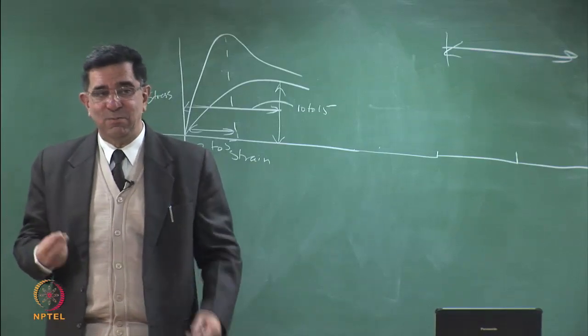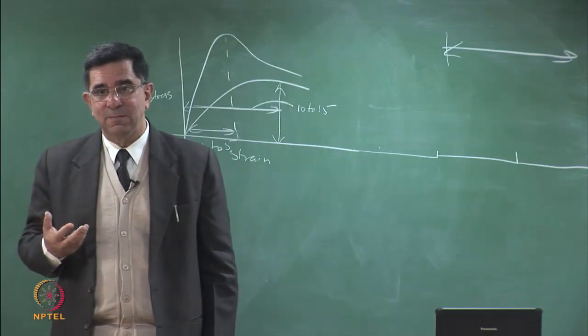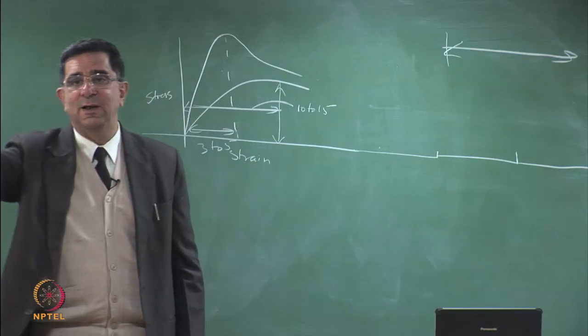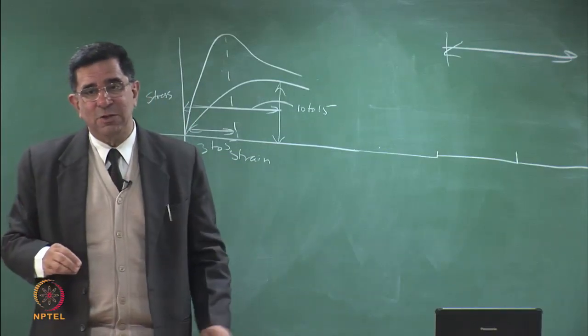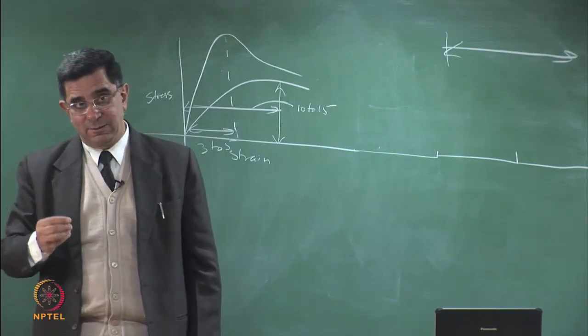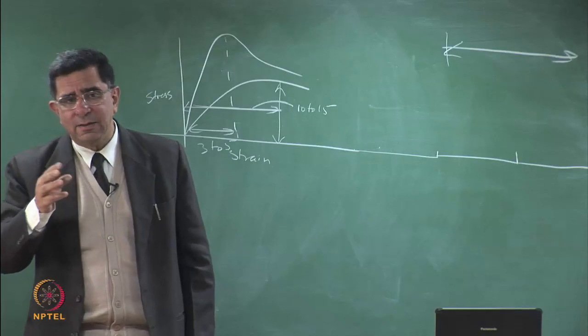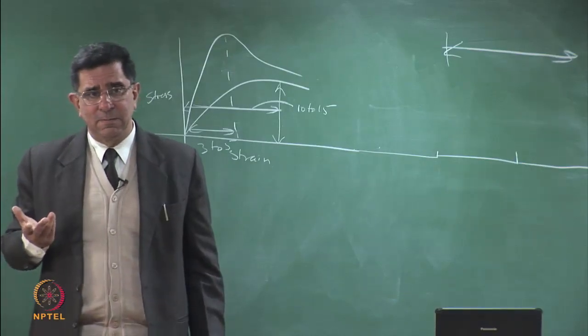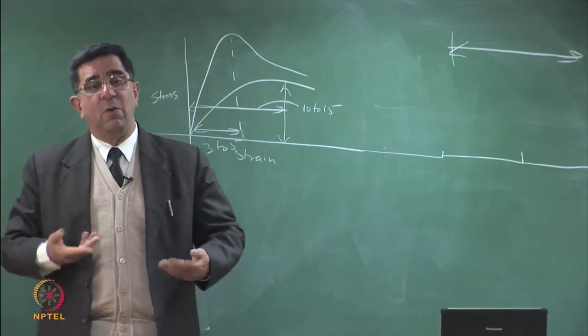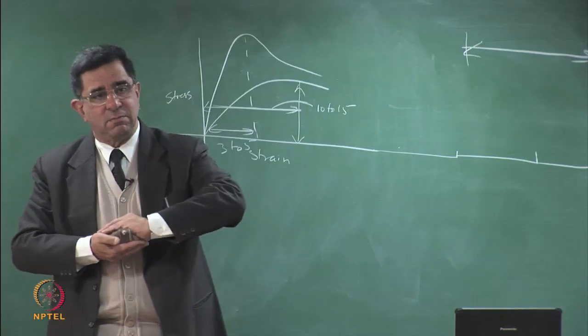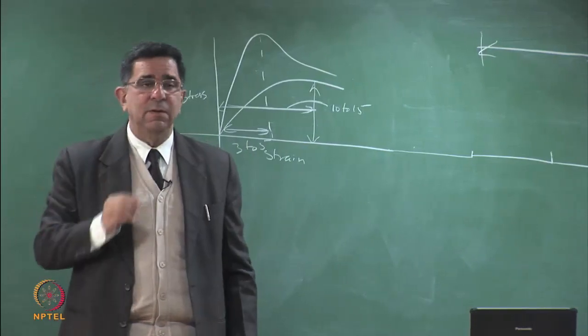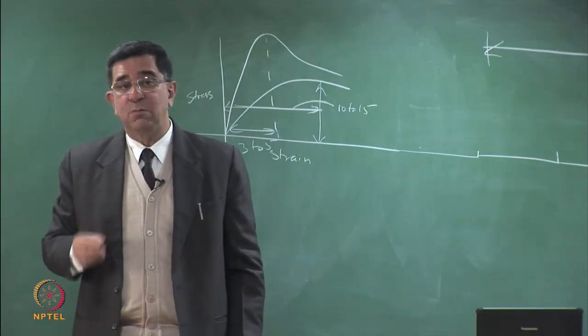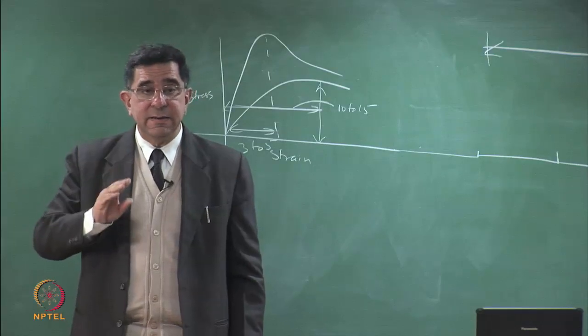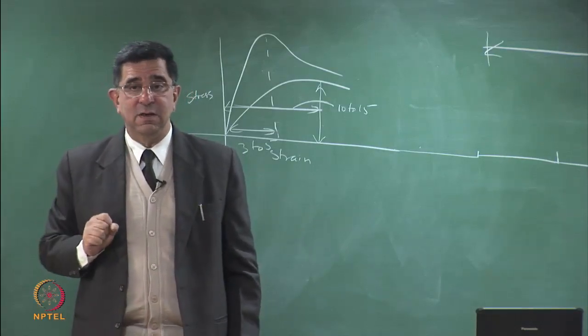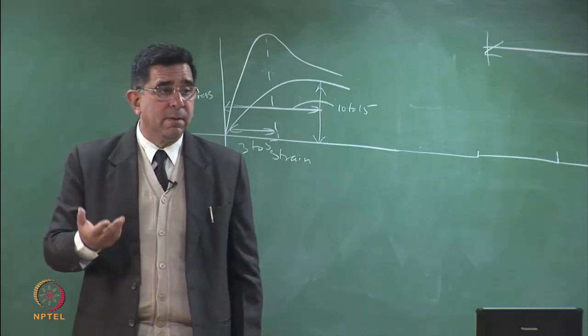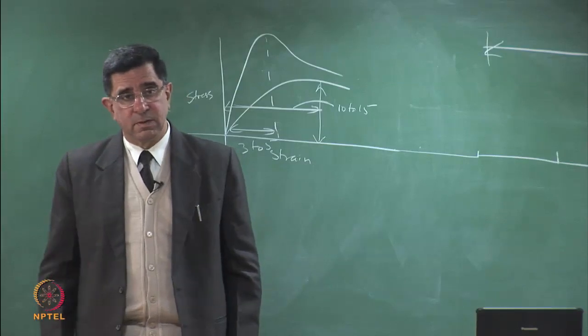Right? Well, here you can't put the two geomembranes in water, but you can take a soap solution and put it along the joint, and you can apply the pressure, and wherever there is a leak, that soap solution will form bubbles. And sealing it is no problem because you heat it and it is sealed. How is the weld made? It is just two hot points which are running across. They seal the thing together. So once you have found the leak, you can do a patch weld. You can put an extra patch and heat it, and just like a puncture, this will be sealed. The only thing is locating it, for which typically a soap solution is used. Okay?